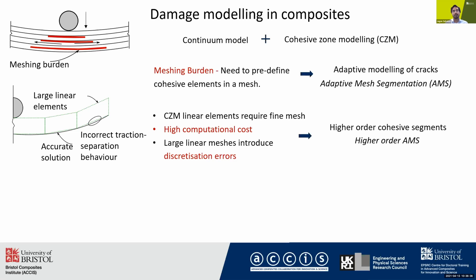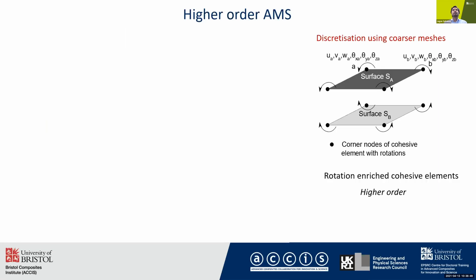This two-step solution is collectively addressed as higher-order AMS, or adaptive mesh segmentation. This is implemented as a user-defined subroutine in LS-DYNA. The kinematics of the novel cohesive element formulation enable discretization using coarser meshes, where vertex rotations are used to model the quadratic displacement of an edge, and multiple integration points can be used to obtain an improved traction-separation behavior.